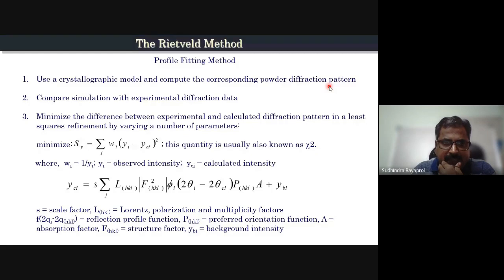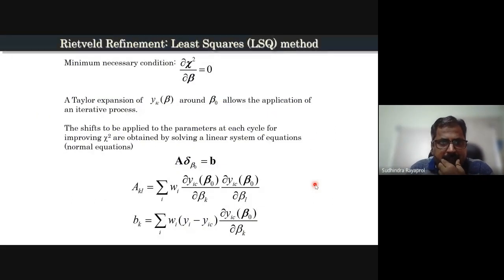And the reason for doing that is to minimize the difference between the observed pattern and the calculated pattern. This is called the least square sum method, because we are trying to reduce the difference between the sum of squares of these two quantities, that is the observed intensity as well as the calculated intensity. Okay, so the calculated intensity is given by this equation, and in a minute we'll come to this equation and see what the important constituents are, which are the ones we are going to refine.